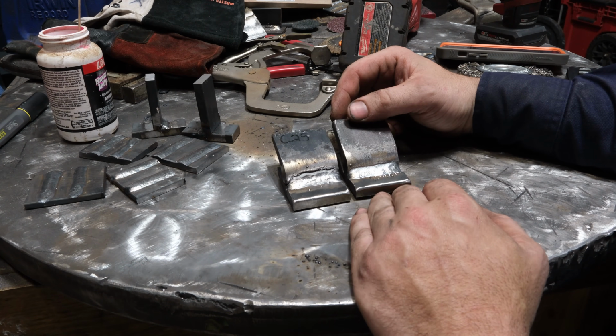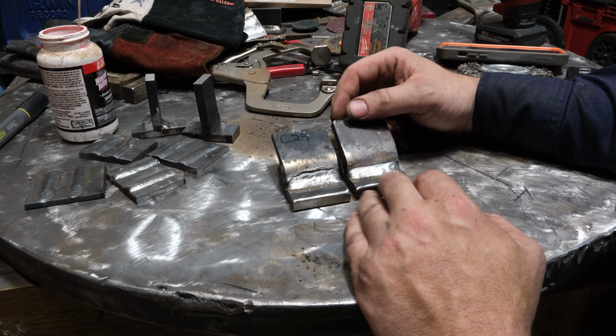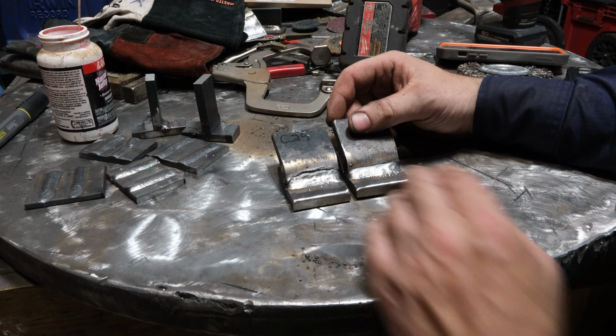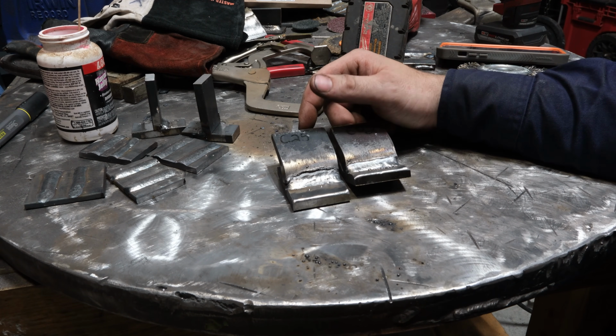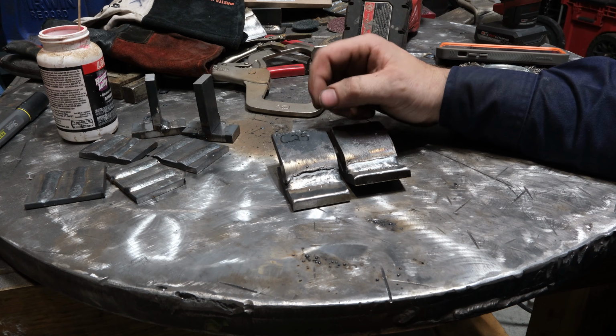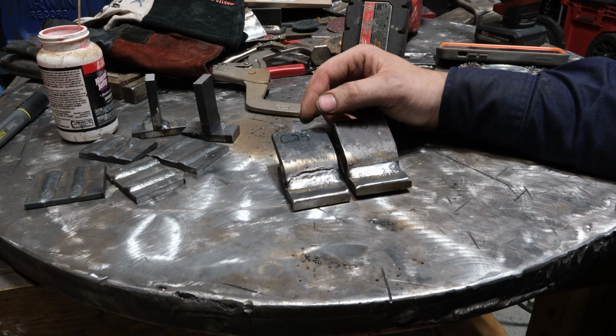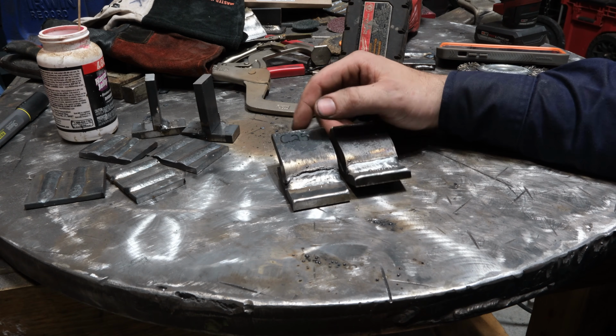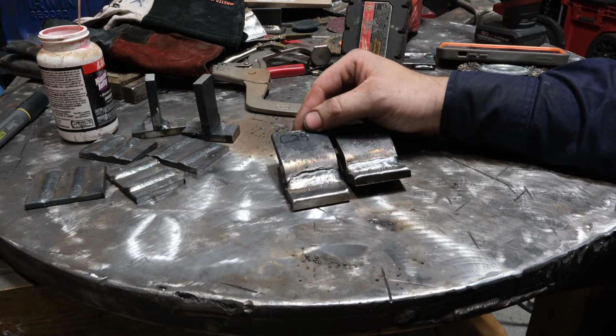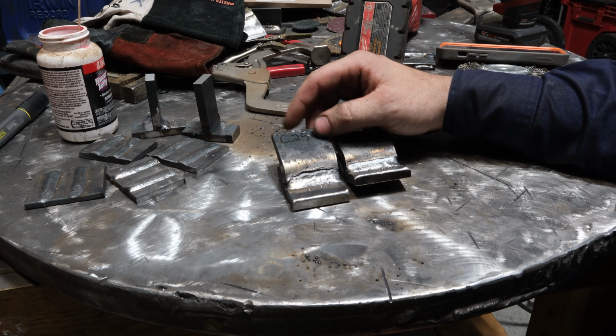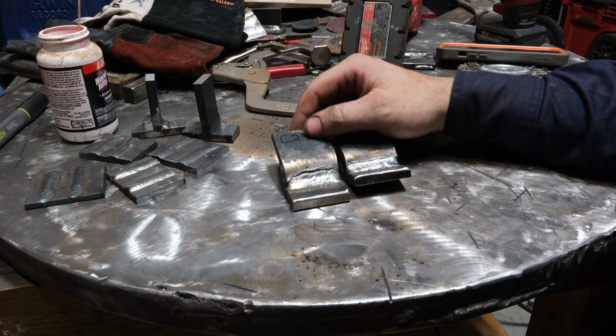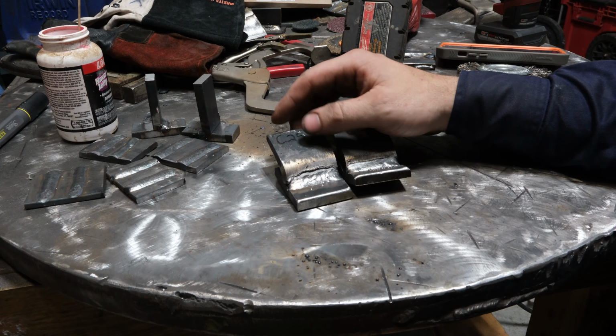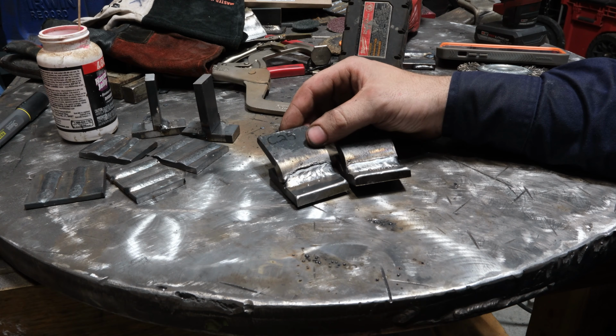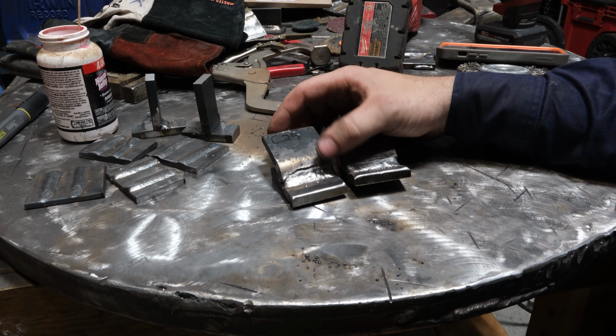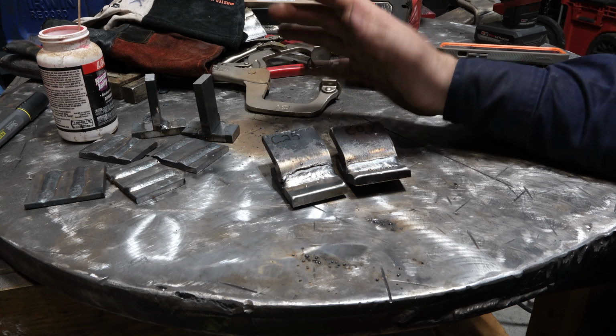Well, the bend test went opposite of what I would have thought, but I think there's a couple reasons. Number one, I should have dialed in these welds a little bit better than what I did. And the biggest flaw that I made with the C25 is I didn't reduce the voltage enough. I dropped it by like 1/2 volt or something, and that simply was not enough. And judging by all of the worm tracks in it, I think that the voltage was simply too high for this, and there likely was some undercut at the top, and that likely contributed towards why it broke. Looking back on the footage, I don't see too much evidence of undercut, but honestly, too high a voltage and the weld defects is a contributing factor, I guess I'll say.